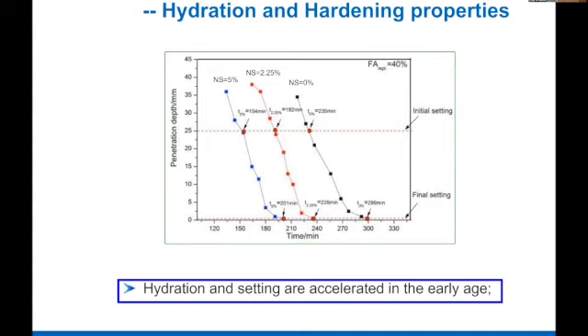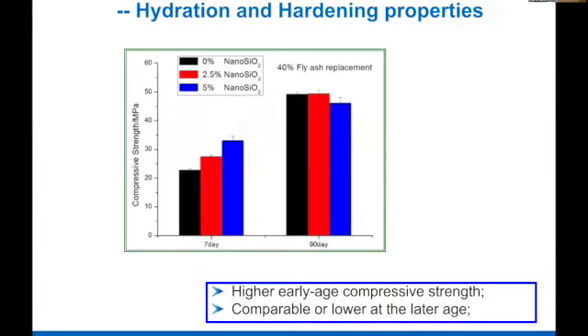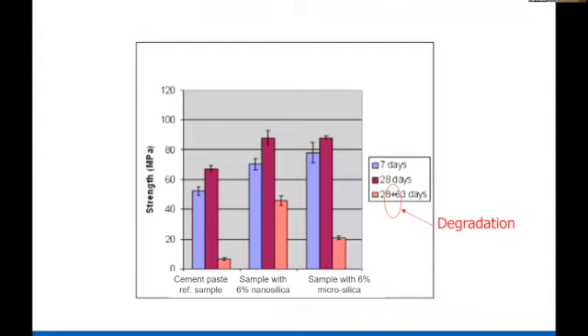And you can see that when we use 5% of nanosilica, the initial set and final set time is substantially reduced. And this is also mimicked in compressive strength at early age. And this is quite important because you can speed up the construction using nanosilica. Not only compression, but the long-term transport properties are also improved substantially by nanosilica. Here, for example, some work we have done jointly with the institute in Spain, where we are measuring calcium leaching. This is very important in storage of waste materials, and calcium leaching means reduction in strength.